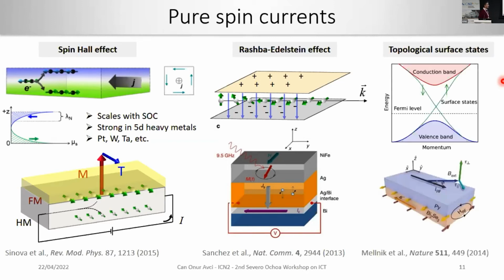And finally, I would like to mention the topological surface states in topological insulators. Because of the special band structure of topological insulators, you have no charge current going through the bulk of the material, but only the surface is conducting. But it's not only conducting, it's also spin polarized. So it's purely spin polarized, and it's an extremely robust, topologically protected spin current generation in materials. And it has also been demonstrated that you can generate very large torques on the magnetization by using this mechanism.